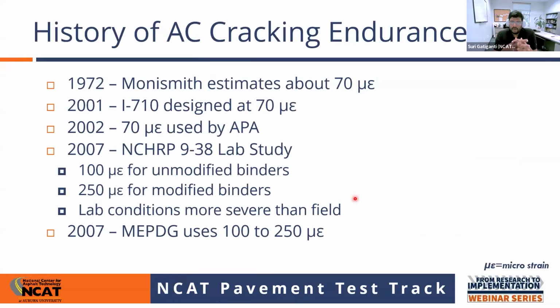And over the years, different researchers have tried to determine if there is an endurance limit for asphalt. In steel, the endurance limit is a big concept. In 1972, Dr. Monismith, with his research from UC Berkeley, came up with a number of 70 microstrain. If you're applying a strain less than 70 microstrain, that material is going to be perpetual, or that pavement is going to be perpetual. And they used that basically for the I-710 project, which is that 70 microstrain.